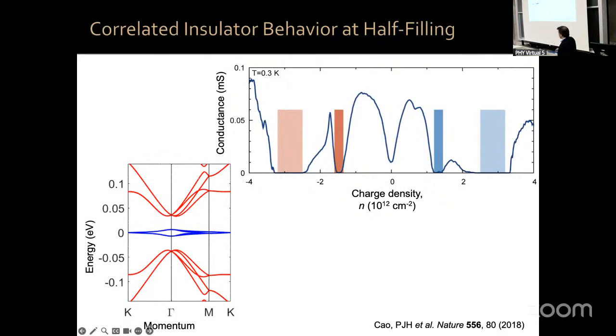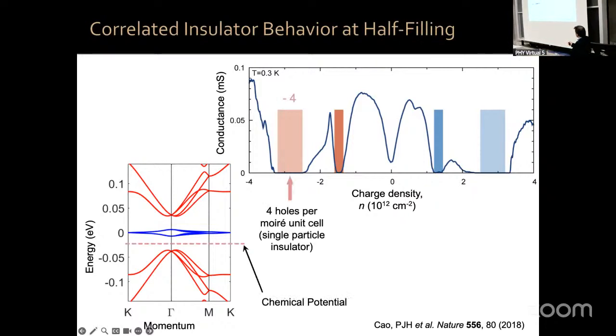And remember number 4. I told you it would appear again. So if we start from zero energy, from what we call the charge neutrality point, if I remove 4 electrons, or equivalently I add 4 holes per Moire unit cell, my chemical potential goes from 0 all the way to the middle of this single particle band gap. As a result, because now my chemical potential is in the middle of a band gap, I don't have available states to conduct electricity for my electrons, and I get an insulator.